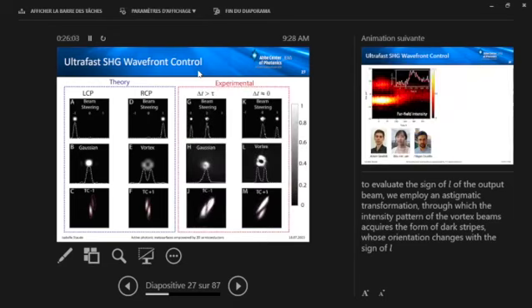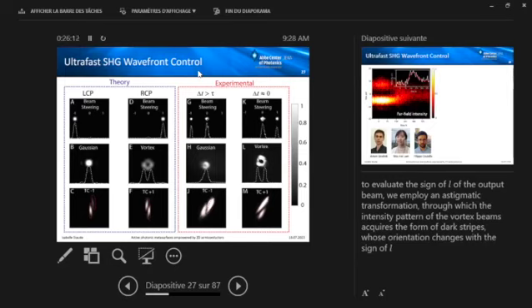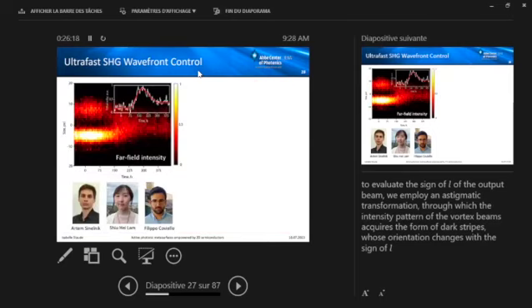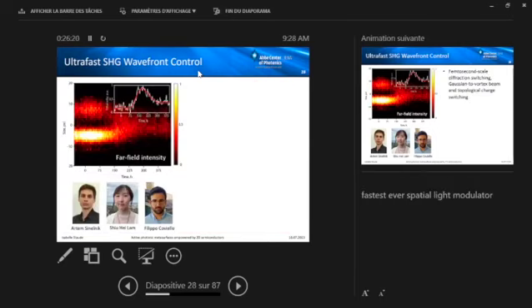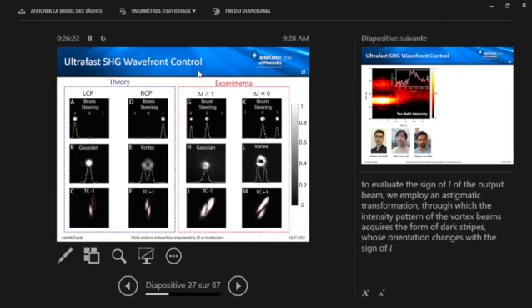Now comes the interesting part. This is the experiment. And note, this is now not just changing the incident circular polarization, but instead, this is an ultrafast experiment, where we are coming in with pulses of about 250 femtosecond lengths. And they are either arriving one after the other or simultaneously, so delay time of zero. And if we then look at the output of the system, we basically can reproduce all of these effects quite nicely. So this seems to work well.